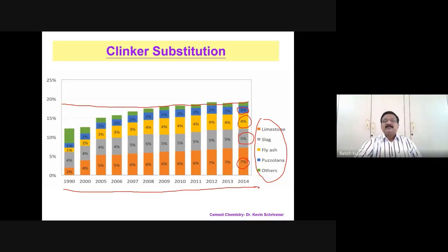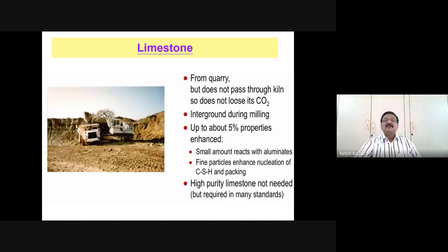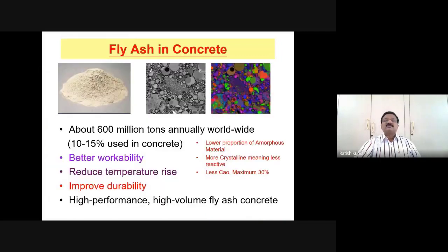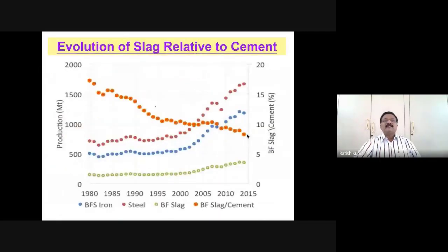And out of these, as you can notice from this particular slide, a large amount of material is available in the form of limestone. And if you go to this slide, we talked about this. As you can notice, the amount of slag which is available is very less, about 8%. We require a greater amount of fly ash and slag, but the amount of slag available is less.